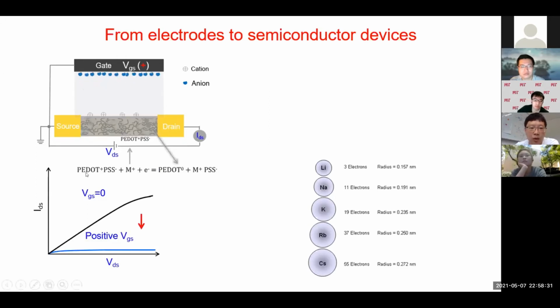And then you have electrochemical reactions happen, which is PEDOT:PSS. PEDOT is positively charged, which is oxidized, compensated by the PSS, which is kind of to charge balance, neutralized. And then because you have this kind of positive ions come, and then you take another electrons from the source or the drain, you will reduce the PEDOT to 0 state. PEDOT, if you reduce it, is not conductive anymore because you lose the conjugated system. You break the conjugated system. And then the conductivity will decrease a lot.